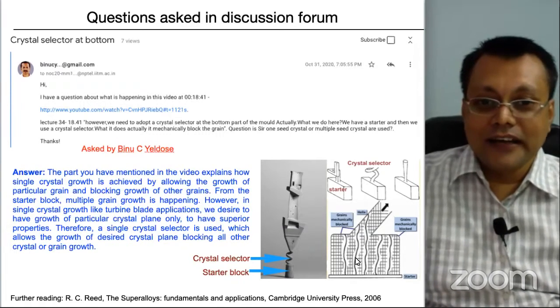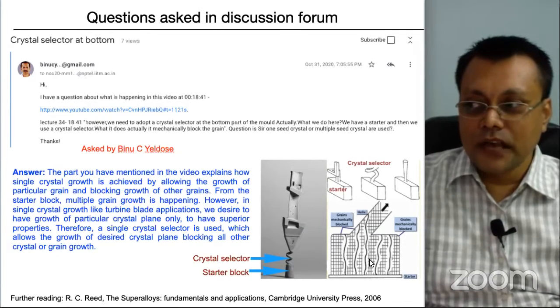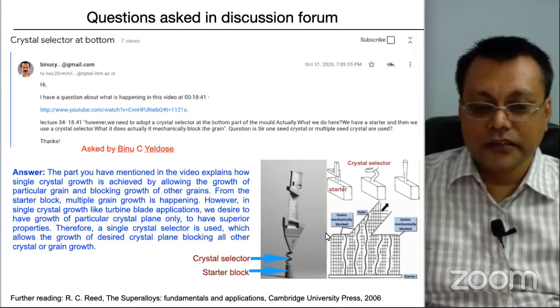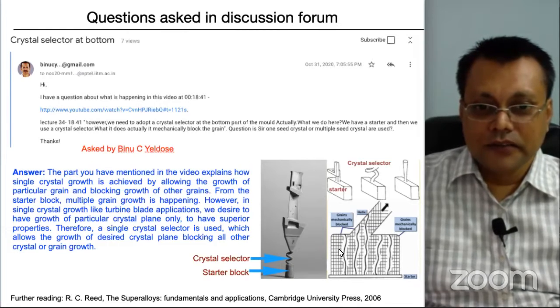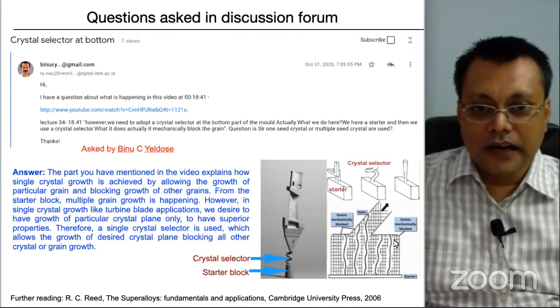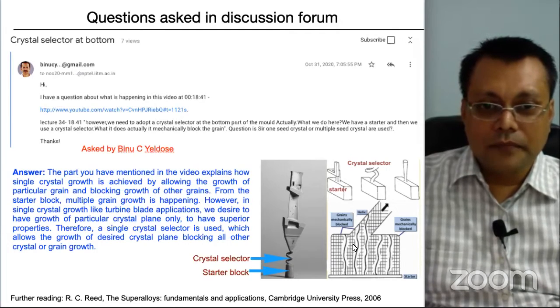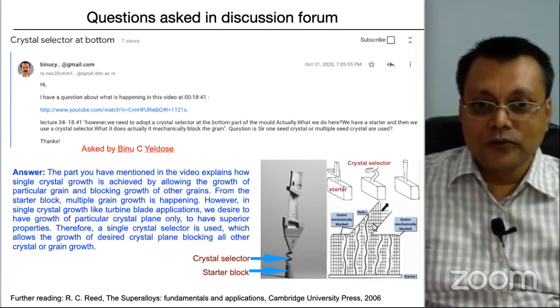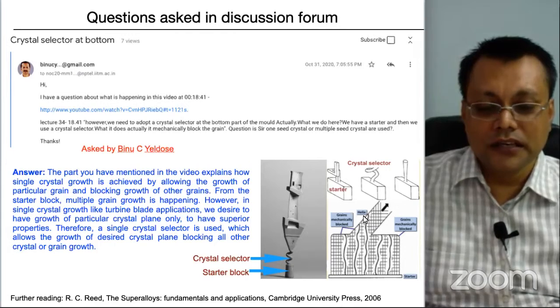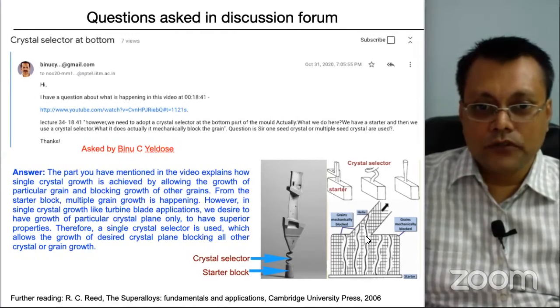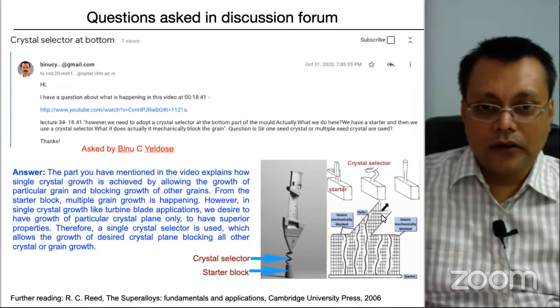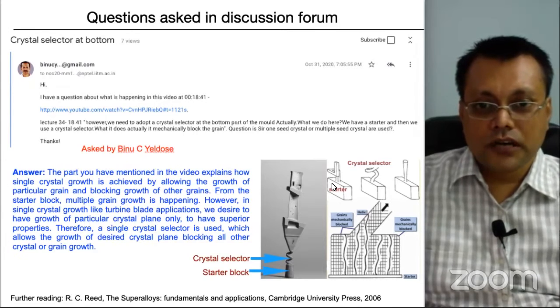Oh no, here this is a very specific case. You please have a look at this particular figure, so then you will understand it better. So we have basically here many different crystals. So this is a seed, and then we have a part that you have mentioned where we allow them to grow into this direction. So this grain boundary should grow along the direction of the heat extraction, and therefore these grain boundaries are mechanically blocked, and only a single crystal can grow starting from the starter.